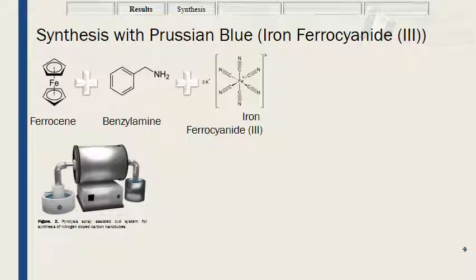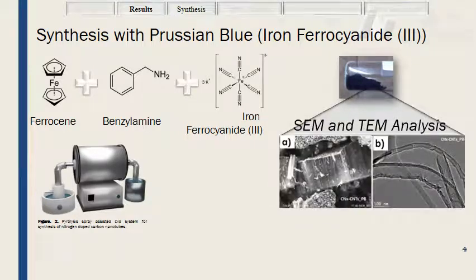Once the synthesis was carried out, the soot obtained was characterized by several techniques, showing the typical carpet-like morphology in which the carbon nanotubes arise well aligned. Another micrograph presents the representative formation of bamboo-type nanotubes, a typical feature reported for multi-walled nanotubes doped with nitrogen.